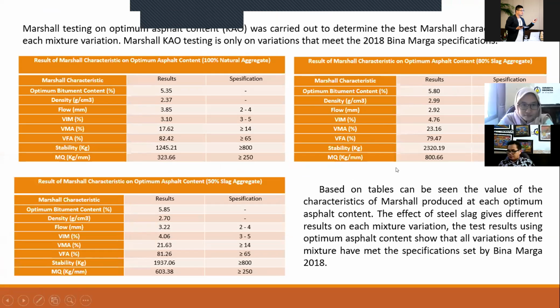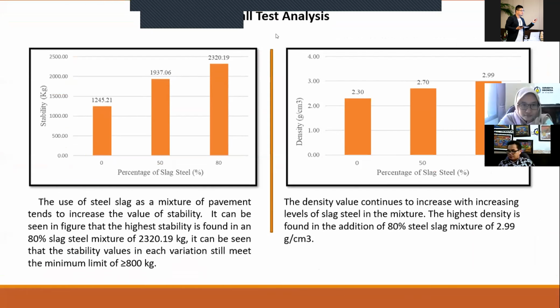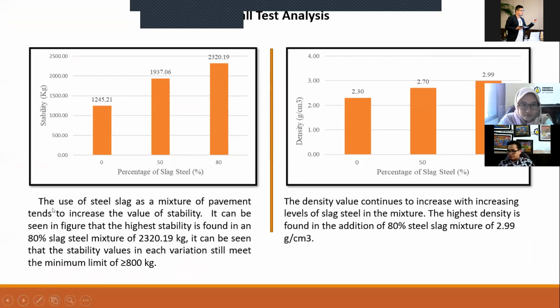Based on the table, can be seen the values of the Marshall characteristics produced at optimum asphalt content. The effect of steel slag gives different results on each mixture variation. The test results using optimum asphalt content show that all variations of the mixture have met the specification set by Bina Marga 2018. And then this Marshall test analysis shows the impact of slag on stability value. The use of steel slag in pavement mixture tends to increase the value of stability.